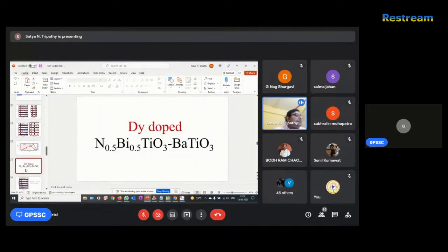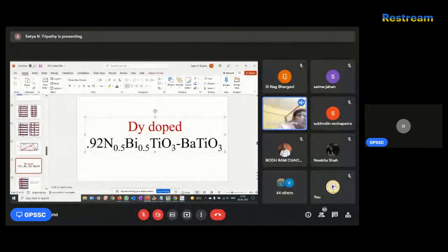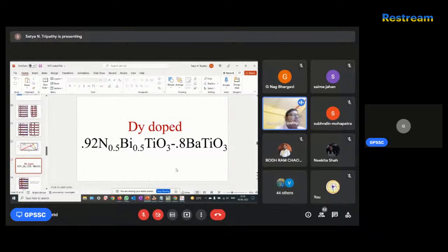So next is another type of sample, the Dy doped NBT-BT sample. So here we had 8% barium titanate and the remainder sodium bismuth titanate. In that, I'll write it: this is 0.92 and this is 0.08. So this is the sample we are dealing with. So here we have doped dysprosium. You see, dysprosium can go to the sodium side, bismuth side, or barium titanate side. We don't know, but we are going to show you how this is determined.